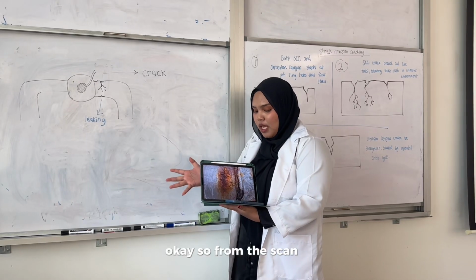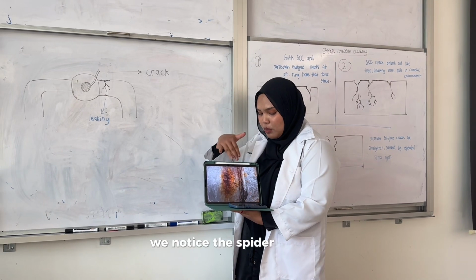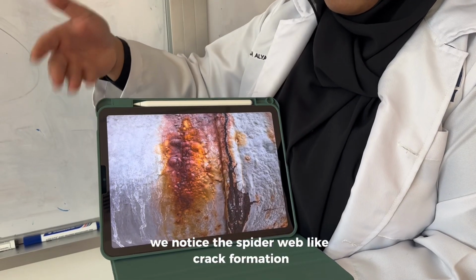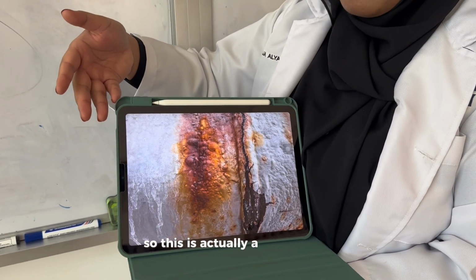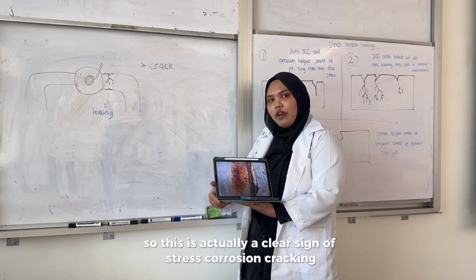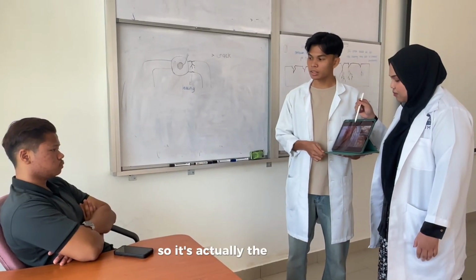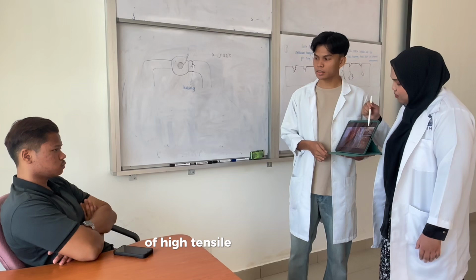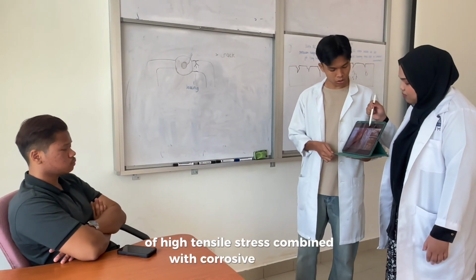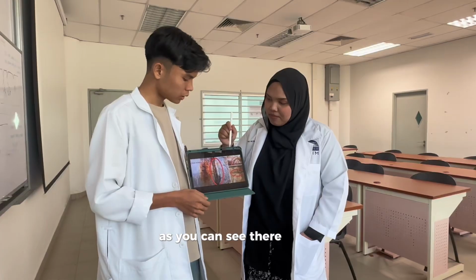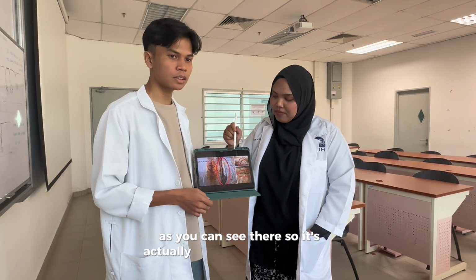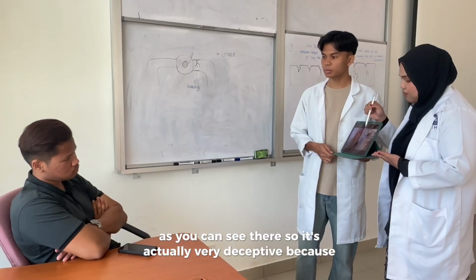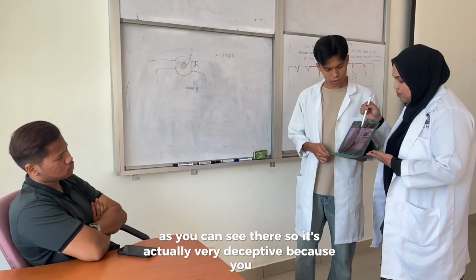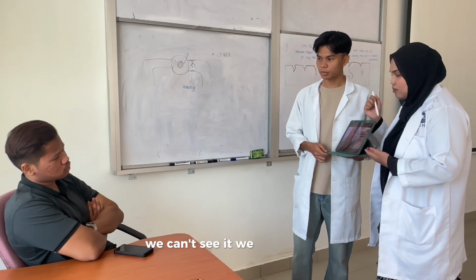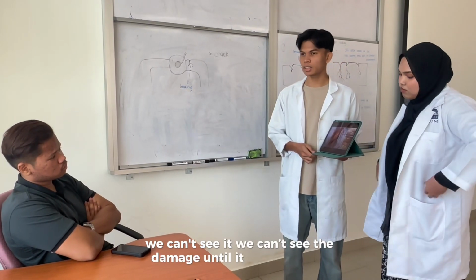Okay, so from the scan, we noticed a spider web-like crack formation. This is actually a clear sign of stress corrosion cracking. It's the result of high tensile stress combined with corrosive chemicals, as you can see there. It's very deceptive because we can't see the damage until it suddenly fails.